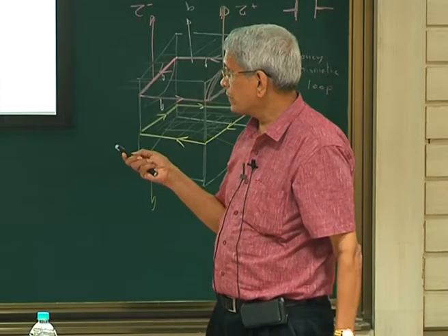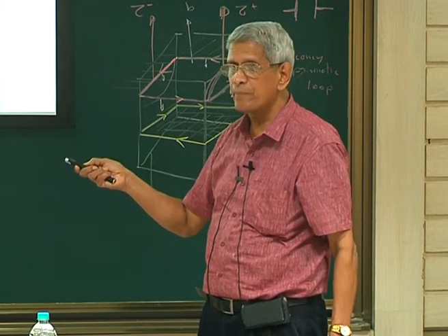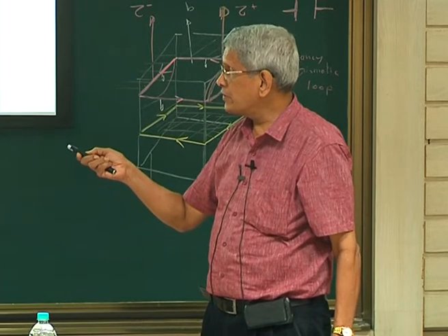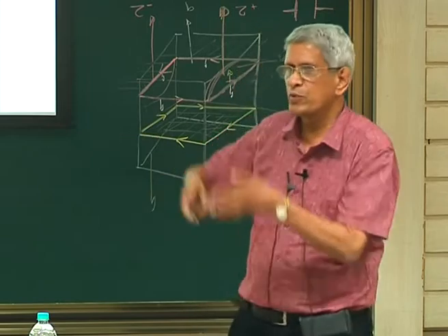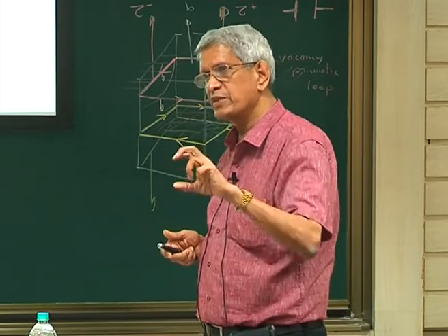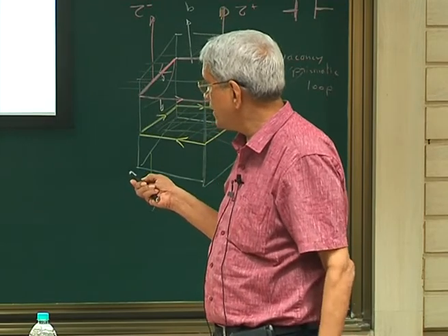So here, if you look at it, as the beam passes through the sample in the transmitted direction, depending upon how it is scattered, the intensity of the beam gradually comes down. There is a distance over which the intensity of the beam can become 0. That distance is called xi g.